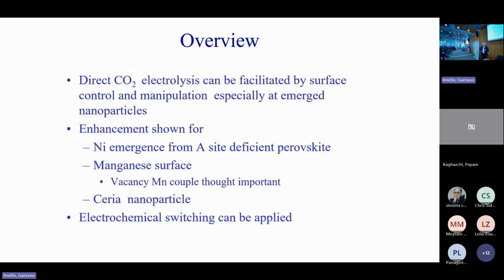So summarizing all this, we can facilitate CO2 electrolysis by surface control. Nickel exsolution is beneficial. A manganese surface with oxygen vacancies nearby is useful. Cerium is ideal, and if you're making a commercial type system, you might well infiltrate cerium oxide, or a cerium oxide layer on top of the A-site deficient perovskite.